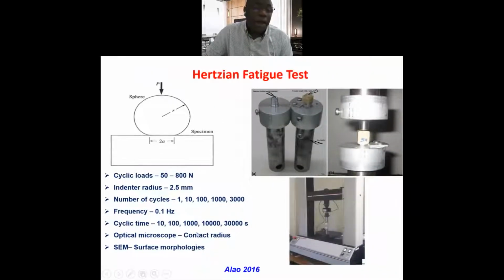Now, in order to determine the reliability of the test, we carried out an Hertzian fatigue test, and this is the experimental setup. You can see this is the conditioned surface, and this is the spherical indenter, and they are mounted like this on a universal testing machine, UTM. And these are the experimental conditions. You can see the radius of the indenter.